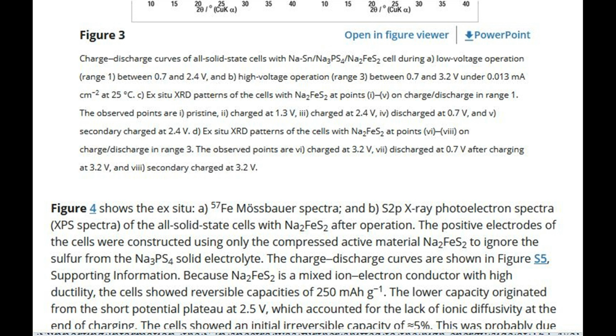d, Ex situ XRD patterns of the cells with Na2FeS2 at points 6 to 8 on charge/discharge in range 3. The observed points are 6, charged at 3.2 V, 7, discharged at 0.7 V after charging at 3.2 V, and 8, secondary charged at 3.2 V.